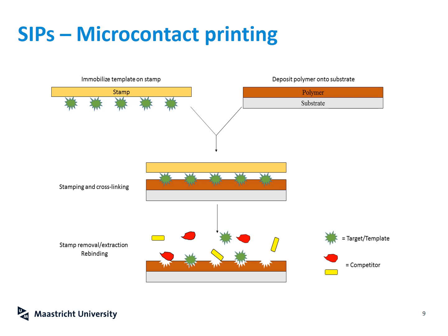form a rigid layer. So what you can do then is take a stamp, immobilize a monolayer of cells, in our case we use E. coli a lot, and push these cells into the layer. And the layer, like I said, is still soft enough, so it will deform and will make molds around these targets, around these E. coli for us. Now, when you polymerize the mixture, the layer will become hard overnight, but will also interact non-covalently